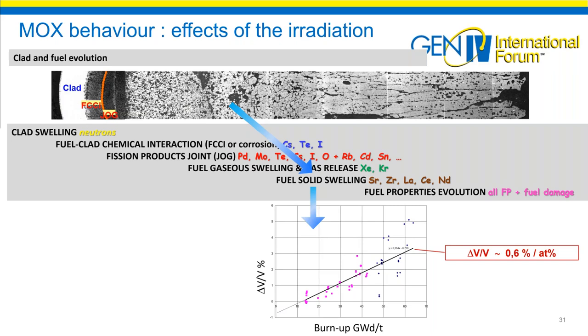Another important effect of radiation damage is the solid swelling of the fuel material. This is due to the increase of the number of atoms inside the fuel with burn-up, and this leads to the increase of the fuel volume. As two fission product atoms are created when one heavy atom is consumed, the total number of atoms is increasing. We explain on this figure that we have a linear dependence of the solid swelling with the burn-up. It has been evaluated to 0.6% per atom percent, which is very low compared to the other fuels. So next slide, please.